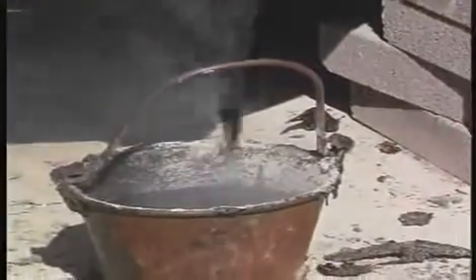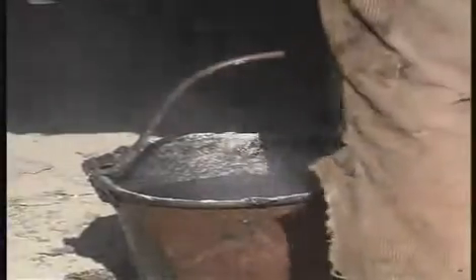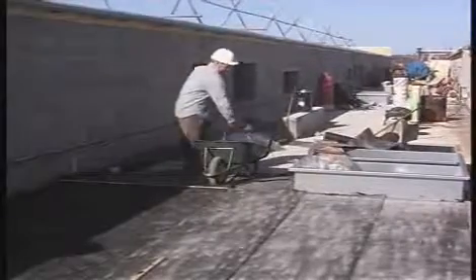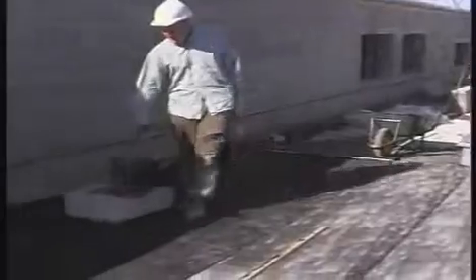The thickness of the asphalt is related to the function of the roof. It's normally applied in 2 10mm coats. At this thickness, its weight is sufficient to resist wind uplift. Additional coats, possibly containing grit or fine aggregates, can provide a suitable surface for areas of traffic, such as multi-storey car parks.